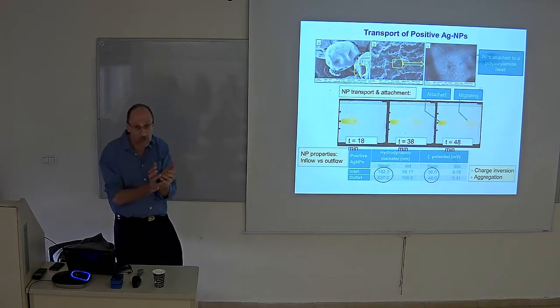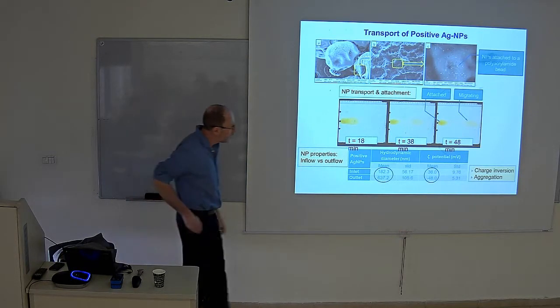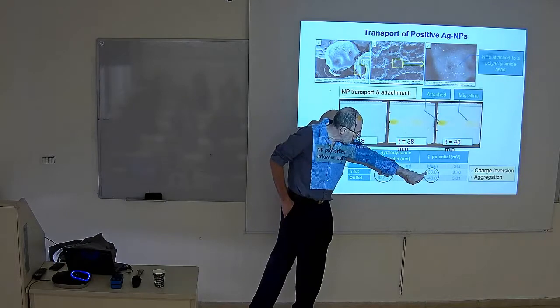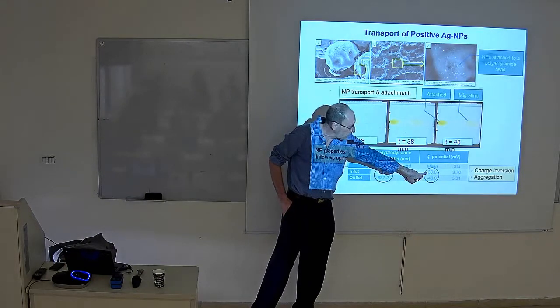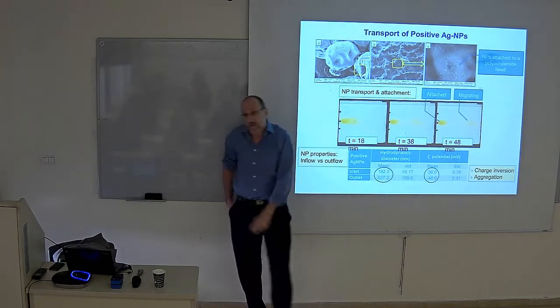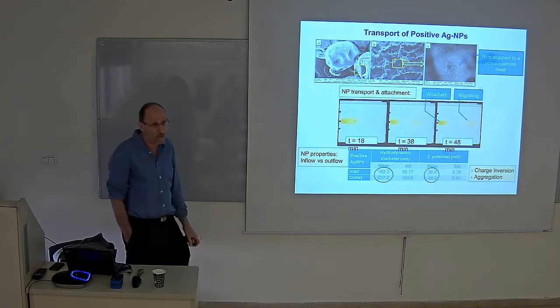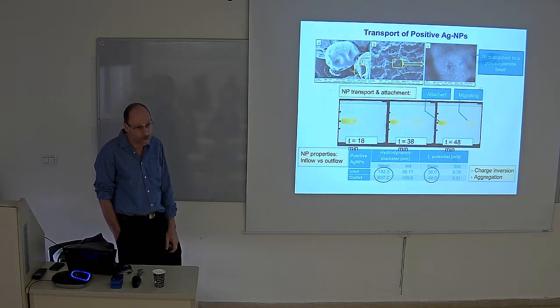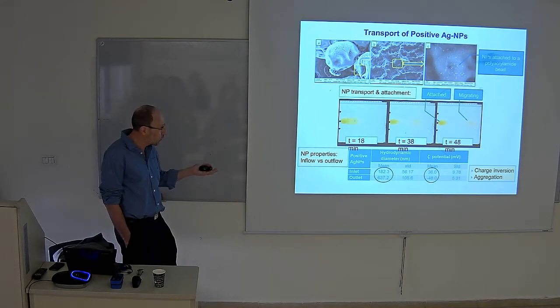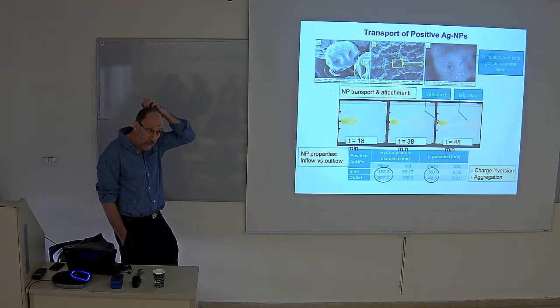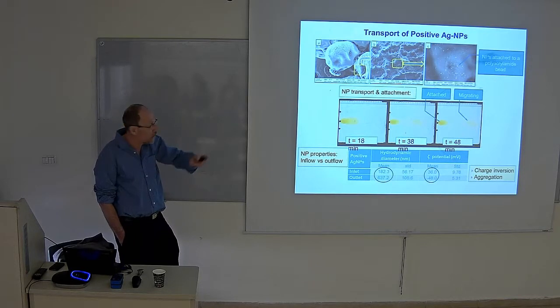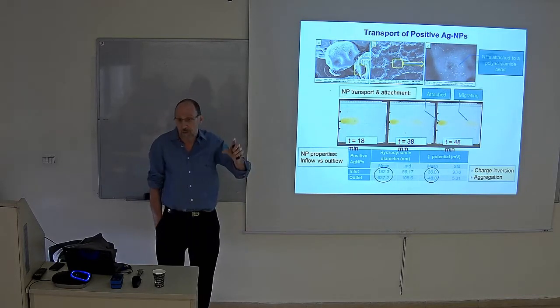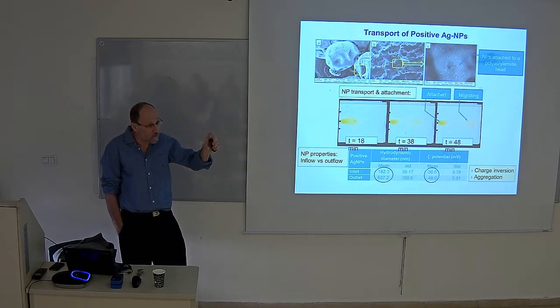So we're getting the aggregation of nanoparticles on one hand, but the other key point is if they started off stable and positively charged, within a short time, they're very stable but negatively charged. So we actually have charge inversion of the nanoparticles, which we really didn't expect. At this point, we didn't go into the chemistry behind it, but what it showed us also, and we've done other analyses afterwards, is that you buy from Sigma Aldrich, or you synthesize in the lab your bottle of nanoparticles, you think you know what you get.